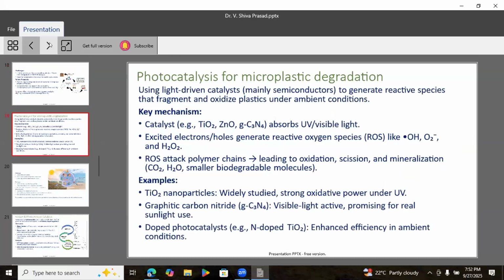Photocatalysis for microplastic degradation uses light-driven catalysts, mainly semiconductors, to generate reactive species that fragment and oxidize plastics under ambient conditions. The key mechanism: titanium dioxide, zinc oxide, and graphitic carbon nitride absorb ultraviolet or visible light, exciting electrons and generating holes that produce reactive oxygen species like hydroxyl radicals, superoxide, and hydrogen peroxide. These attack the polymer chains, leading to oxidation, scission, and mineralization into carbon dioxide, water, and smaller biodegradable molecules. So the polymer degrades into smaller fragments.